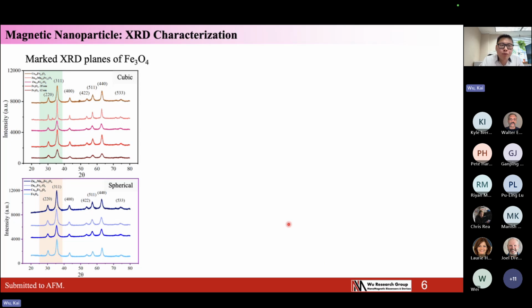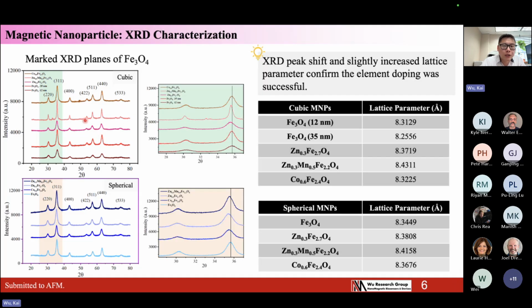So we first calibrate the crystal structure of these particles. I compare the cubic nanoparticles and spherical particles in 2 panels here. We mark the XRD planes of the iron oxide here. As we zoom in on the 311 plane, you can observe the peak shift as we dope cobalt, zinc, and manganese into the iron oxide.